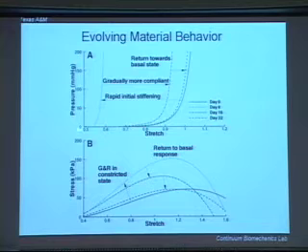And so here what we see is the normal pressure diameter behavior of that vessel, and at 7 days it's stiffened tremendously. And this is the clinical problem. You give a vasodilator, you have a constricted vessel that's very stiff, and you cannot get it to dilate. But as the collagen turns over after the removal of this constrictor burden, you actually do go back within about 4 weeks.